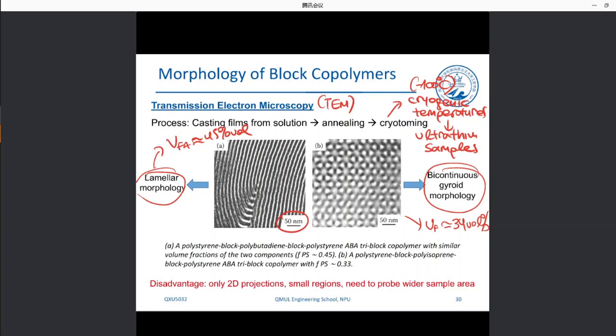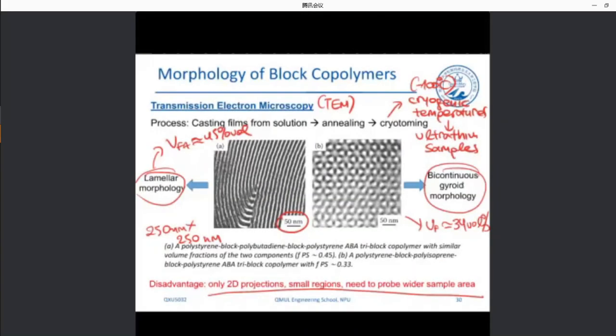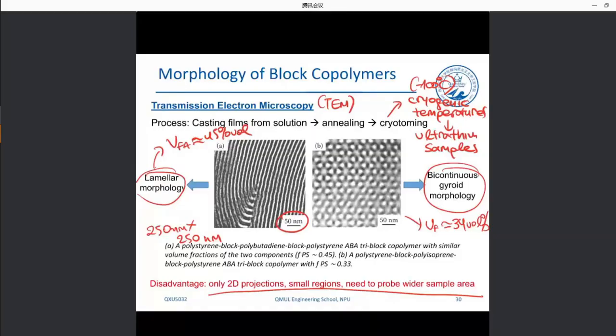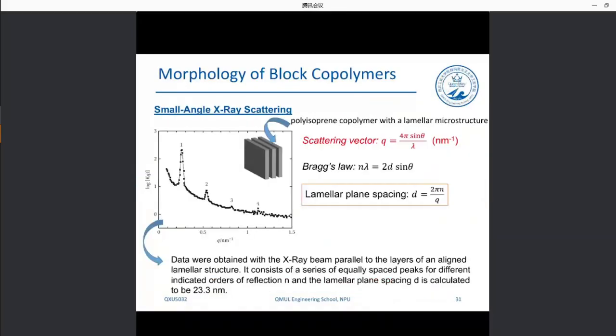This is a scale bar of 50 nanometers. This photo is 250 times 250 nanometers. So we have only small two-dimensional projections, small regions, and we need to understand if the majority of our samples shows these morphologies. Okay, and how do we do that? We do that by using another technique that is called small angle X-ray scattering.